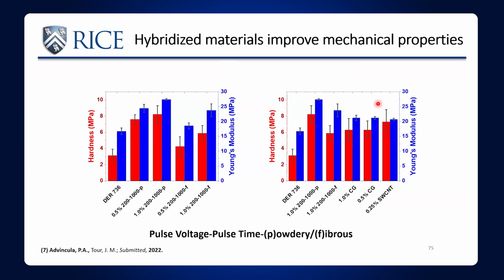And then you can see what happens if you hybridize materials. So this is putting it in epoxies, and you can see what happens when you add more of these to it. The hardness increases. So this is where you just have the epoxy. This is the hardness in red. In blue is the Young's modulus. Now when you start adding in some of this material, you can see these numbers start going up. And so you can get about double on the hardness, and you go up, I don't know, 50% or something on the modulus, the stiffness of the material. And so you see how you can improve materials.